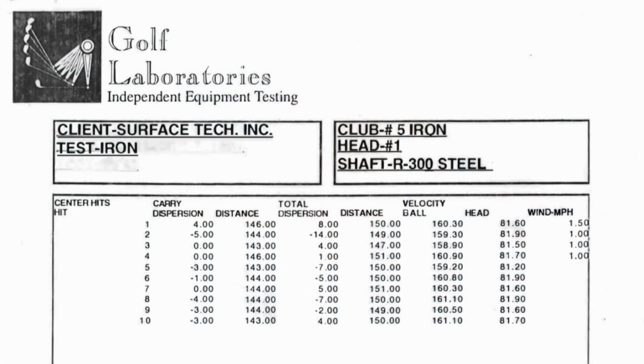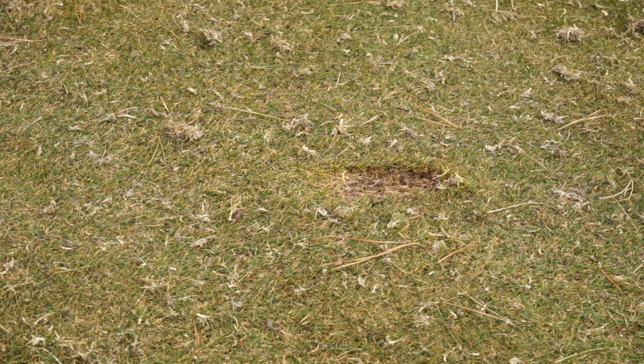We then did the same sort of work with a very controlled experiment with robotic testing for the golf clubs that had the same swing weight, the same club length, the same loft angle. Everything was exactly the same, except one club was enhanced with the composite diamond coating, and we measured in this laboratory test on a fairway an increase of about 7% farther distance. And it's because of the energy transfer that you get when the golf ball is hit by a golf club in a fraction of a second. So that actual physics is incredibly important, and fortunately something that composite diamond coating, with the hardness of the diamond, is able to affect in a very real way, from real tests on golf balls and golf clubs to just seeing it in a laboratory test to confirm the basic physics of this.